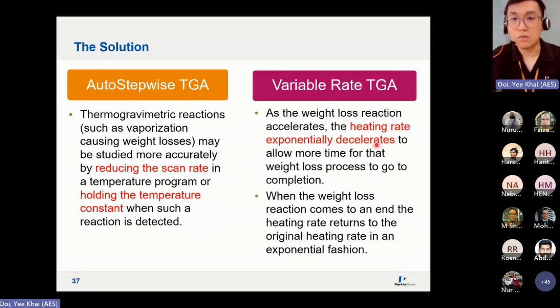Then you have variable rates. With variable rate, we do not control the rates. Instead, what we control is resolution. So the higher resolution that we set, the slower it goes. When it encounters weight loss, the heating rate will exponentially decelerate, and when the weight loss comes to an end, it will return to its original heating rate. So what we adjust here is resolution, but both of them are the same thing. The main purpose is to reduce the time for the analysis while still getting the best resolution as well.